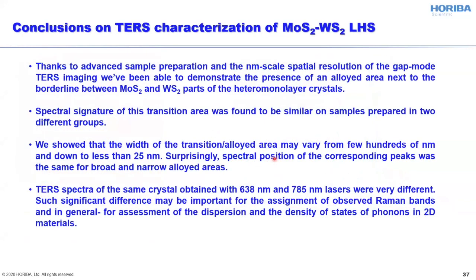Okay, with that, we'll come to the conclusion on the TERS characterization of molybdenum disulfide, tungsten disulfide lateral heterostructures. So thanks to advanced sample preparation and the nanometer scale spatial resolution of the gap mode TERS imaging, we've been able to demonstrate the presence of an alloyed area next to the borderline between molybdenum disulfide and tungsten disulfide in the heteromonolayer crystals. Spectral signature of this transition area was found to be similar on samples prepared in two different groups. We showed that the width of the transition or alloyed area may vary from hundreds of nanometers down to less than 25 nanometers.